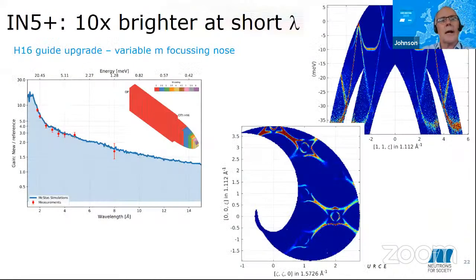So IN5 is another time of flight spectrometer that has had upgrades, but more is still possible. And here we simply changed the end of the guide and added a variable m focusing nose. And this gave a factor of 3 increase in count rate at the sample at nominal wavelength, but almost a factor of 10 at shorter wavelengths down to 2 angstroms. So really increasing the operating range of the instrument.